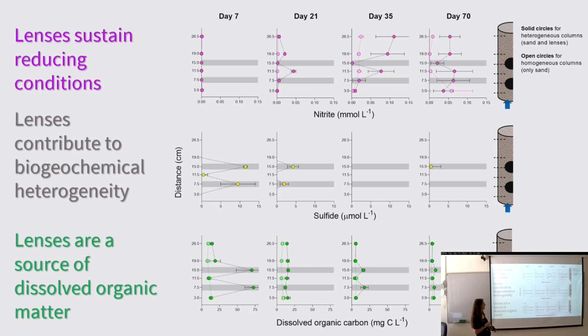So, what we're seeing here is that we have elevated concentrations of nitrite and sulfide within the heterogeneous columns containing the lenses. Now, that shows us that we have a process of denitrification taking place. So we have nitrate that's being reduced to nitrite. Furthermore, you can see increased sulfide concentrations, and that's showing us that we have sulfate reduction to sulfide also taking place. And that shows that these lenses are sustaining reducing conditions both within them and in the succeeding sand. Moreover, we see higher levels of organic carbon released from the lenses, showing that they are also acting as a source of organic carbon.